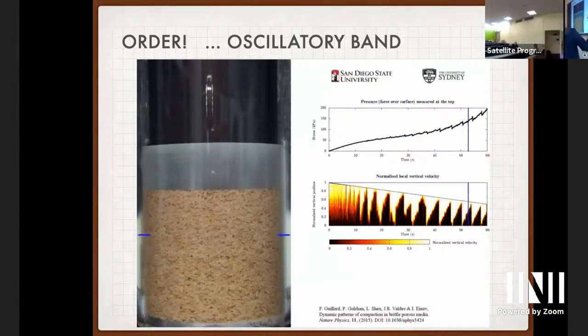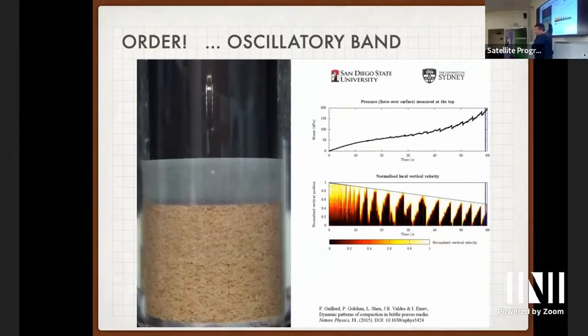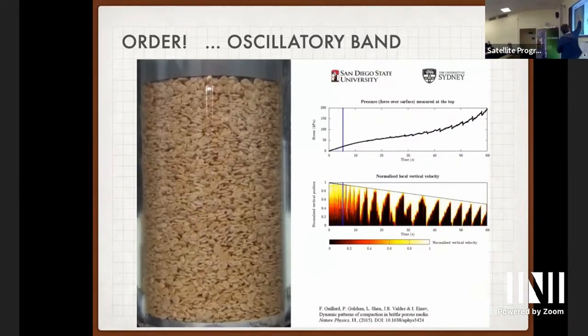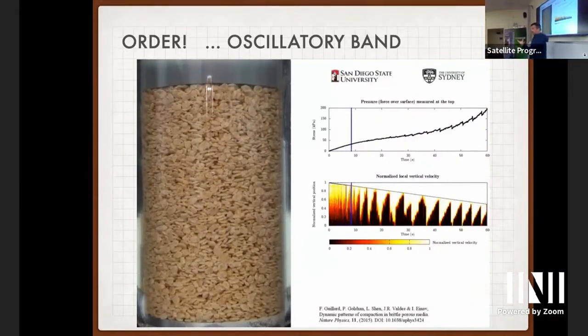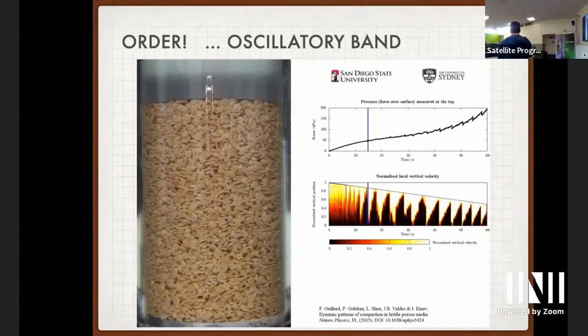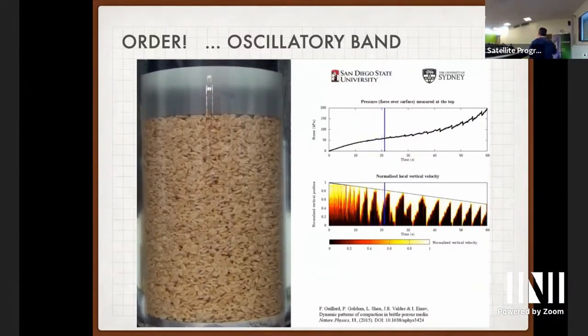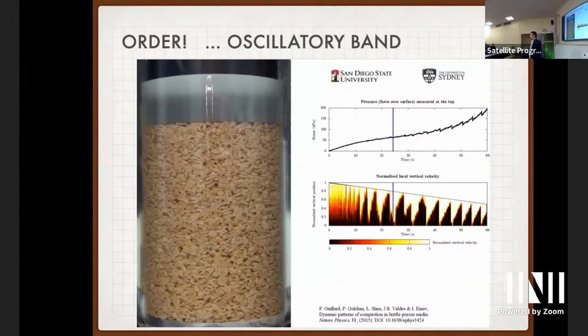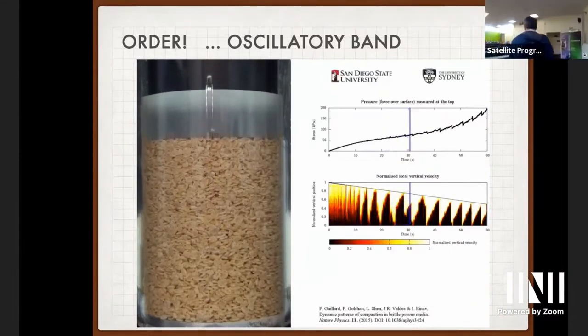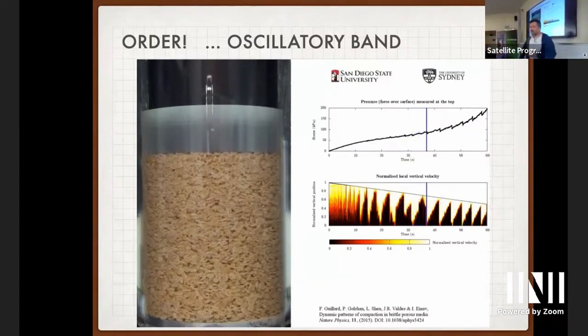What happened is that the stress here at the top is higher, at the bottom is lower. There is the Janssen sort of effect, exponential decay of the stress. And at the top, it's consolidated faster, right? You have more crushing, more core collapse. So the material in a macroscopic, homogeneous sense becomes stronger. It has a higher stress, and gradually it's also becoming stronger. And at some stage, the stress over the strength of the material becomes fairly homogeneous. Although the stress is not homogeneous, the ratio of stress to strength over time gradually picks up this homogeneity, and that's where things start to get this organized behavior.